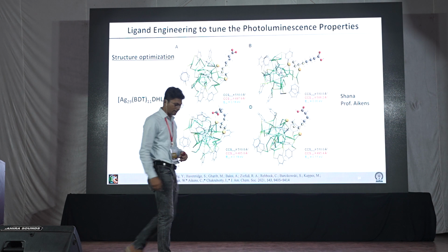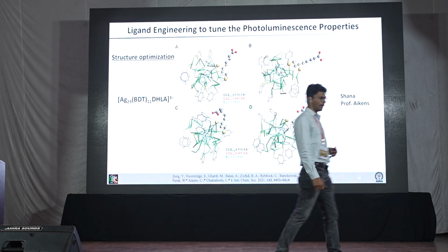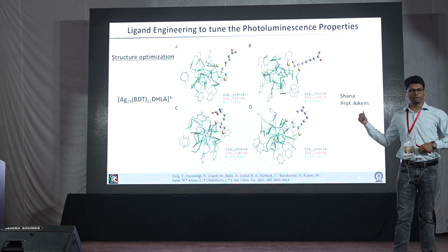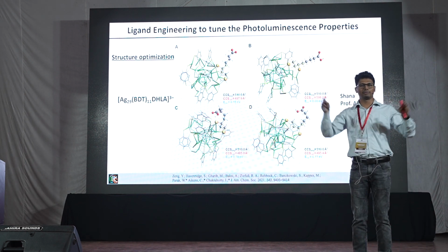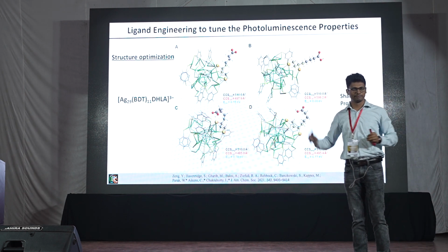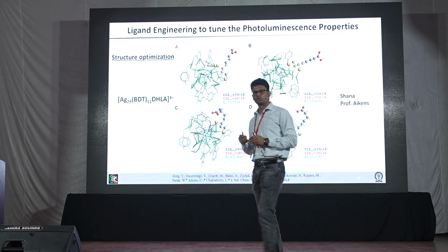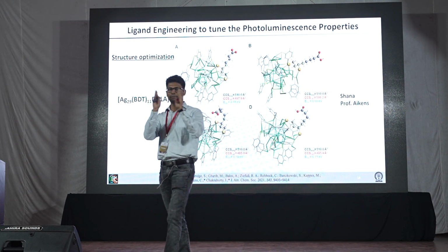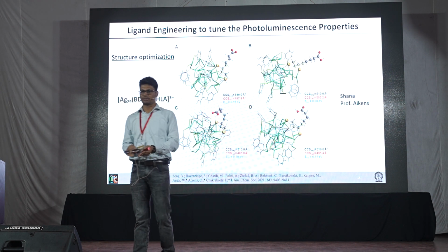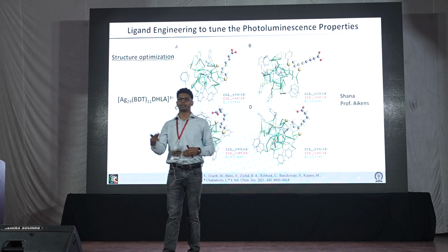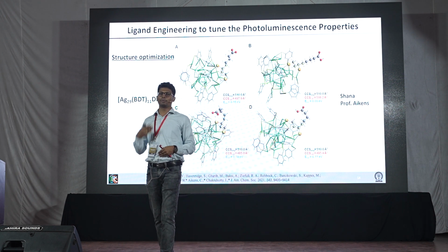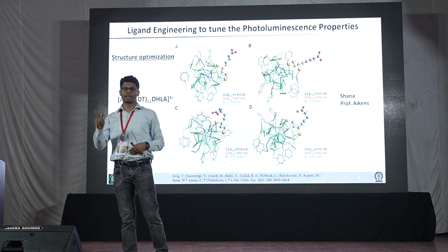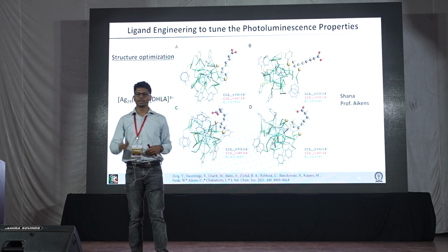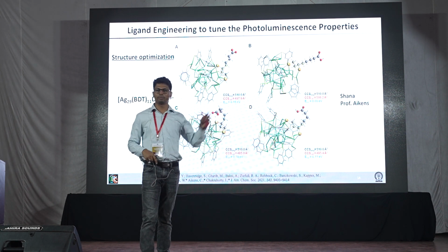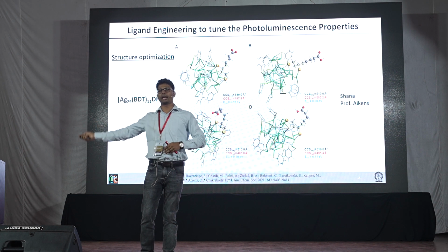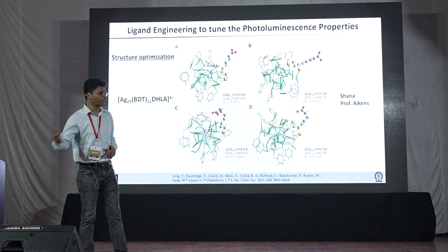In order to know the structures, what we did was an ion mobility measurement. That is what you have seen in the last data, which is basically kind of a DLS that separates ions based on their size. And we also have the possibility to measure that size in the gas phase. So you can trap that ion and get its ionic size, right? And you can also calculate, because if you can design a model, you can calculate. So you have a possibility to know which isomers are present in that particular case, because you can get the CCS value from IMS, and you can calculate it from your theoretical data.